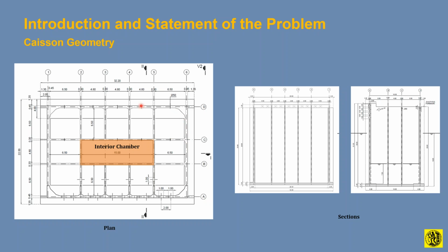The only particularity of this caisson, which was used in the previous construction site as well, was that because the caissons are constructed in dry and then in wet conditions using slip form operations, in order to facilitate the slip forming, the contractor needs a void in the interior of the moving floor, as this caisson is slip formed from elevation 0 at the mud foundation all the way to 29 meters height, so that in this location